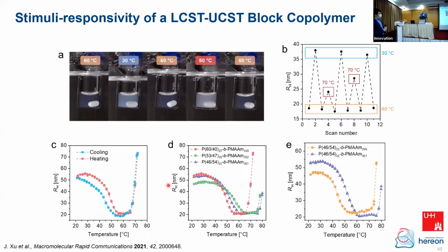While with the UCST in this system we are rather fixed, so we cannot change much there, unless, and this is also what Xing is now working on, another less sensitive system, which is not so easy to hydrolyze. But UCST is really a nightmare. Also, if something is wrong with the water, some impurity or something, all of a sudden the UCST is gone. So it's quite sophisticated.